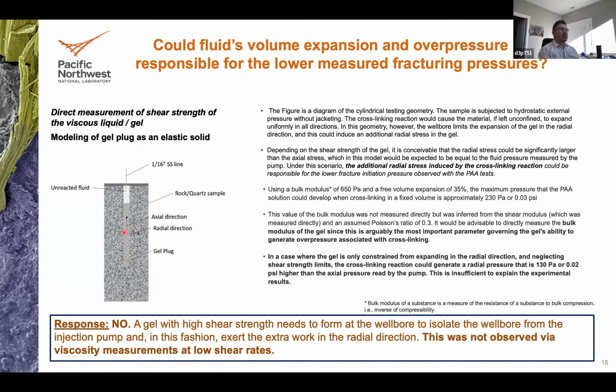And in that way, and only in that way, a radial direction stress will be generated locally. And then the pressures that we measure at the pump, which are lower than for all the other fluids, are because the rest of the pressure needed to get to the values at which we fracture the rock or the fused silica is added by this localized pressure associated to the gel expanding in volume.